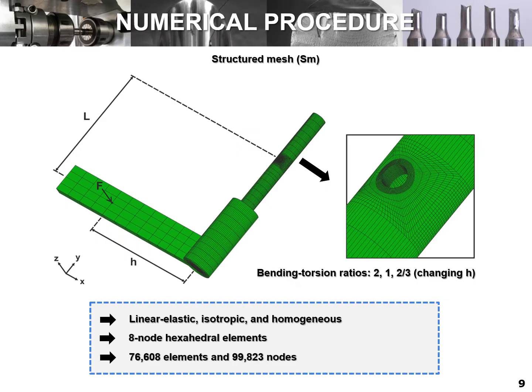Regarding the numerical procedure, as referred to above, we have developed two independent finite element models. In both cases, it is assumed a linear elastic, isotropic, and homogeneous behavior. The structured mesh created in a parametric manner from 8-node hexahedral elements is presented in this slide. It has an ultrafine ring of elements at the hole region to characterize in detail the stress-strain response at the critical area. The bending moments and torsion moments required to apply the BT ratios were defined by a single force F, positioned at different locations of the prismatic bar connected to the specimen.